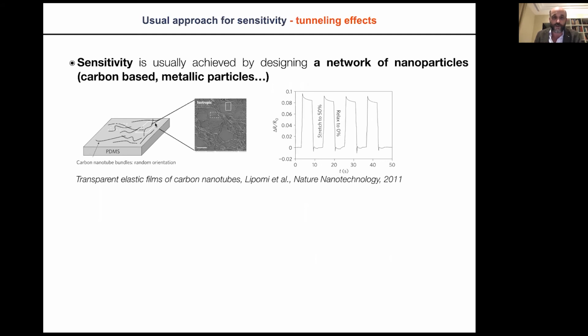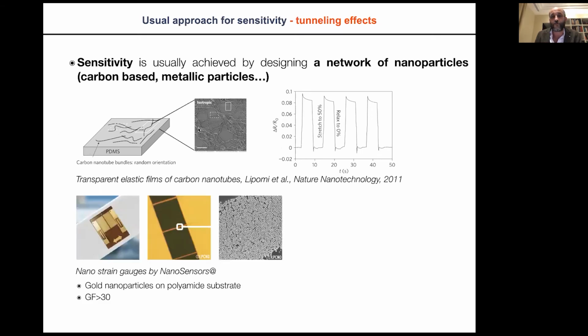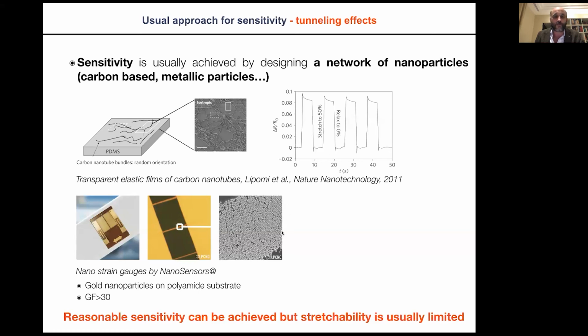So, for example, this is a coating of carbon nanotubes on PDMS, and you see that you have a change of resistance. The sensitivity is usually achieved by the morphology of this network, but here you get a sensitivity that is limited, with a stretch that is relatively limited. I mean, you have some sensors on the market that are also based on metallic nanoparticles like this, but are using exactly the same concept. You can get a gauge factor of 30. But here you see that the stretchability is limited because you are working on a polyamide substrate. So you cannot stretch this, and as soon as you get a real separation of your particles, you don't have conduction anymore. So you cannot use it as a sensor up to 50, 100, 150%.